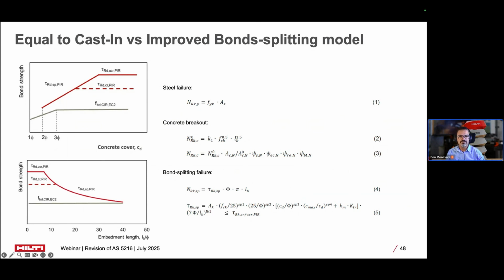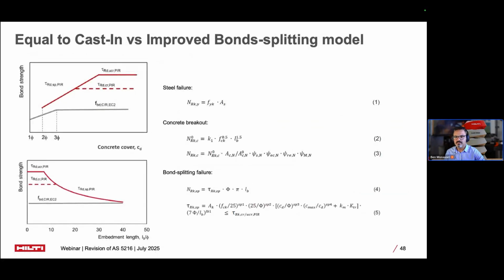Similarly, the improved model shows varying bond strength with embeddment depth, reflecting actual load distribution behavior rather than a constant relationship assumed in equal to Cast-In system. So if I show you here, this is equal to Cast-In graph. Look at how the capacity changes in embeddment depth. This is a bond strength. So the bond strength in equal to Cast-In system is constant. It doesn't really matter on the embeddment depth.